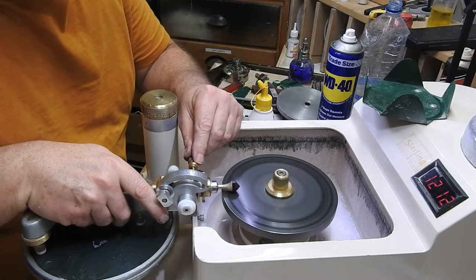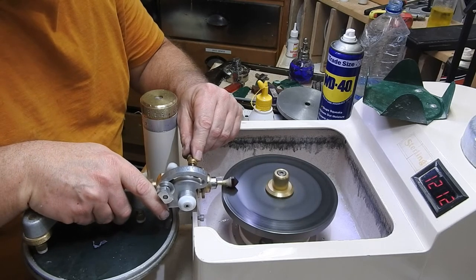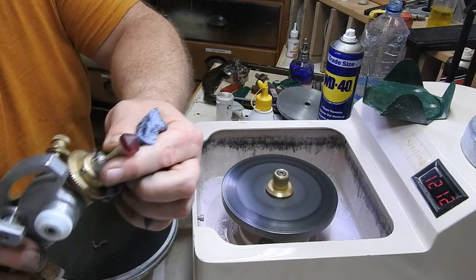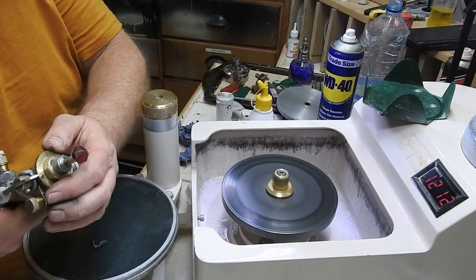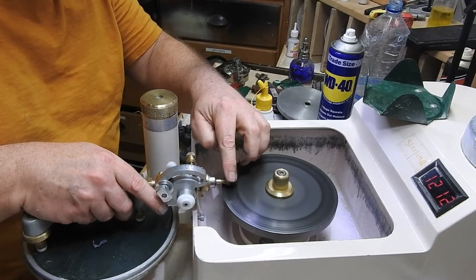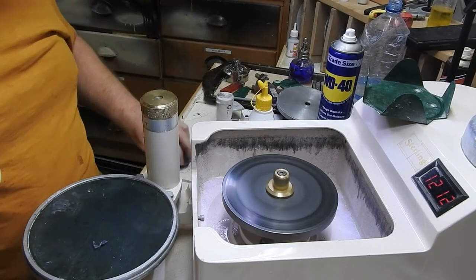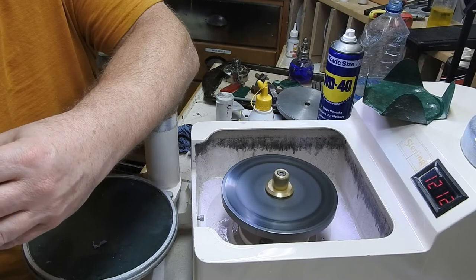So I've got some adjustments going on now with learning how to use this new disc from Sterling, this new lap rather, polishing lap, designed for hard stones. Got rubies and sapphires. I don't know how much you can see, but the ones that I've done are coming up very nicely. That a bit more. I've got it now operating at about 1200 using multi-purpose light oil and 5000 diamond dust, and it works beautifully on that.